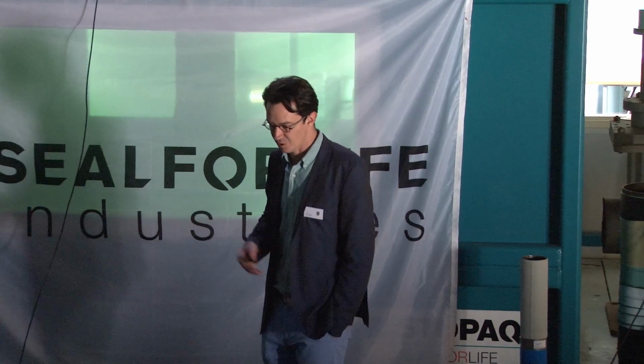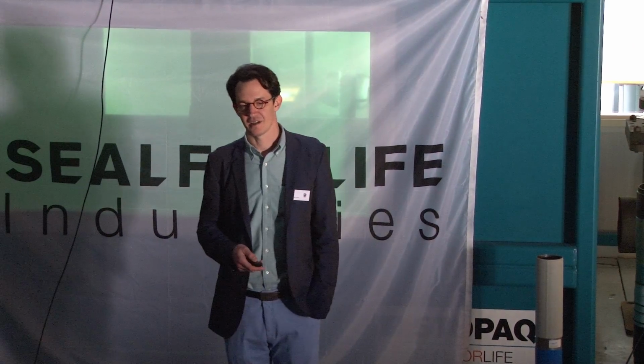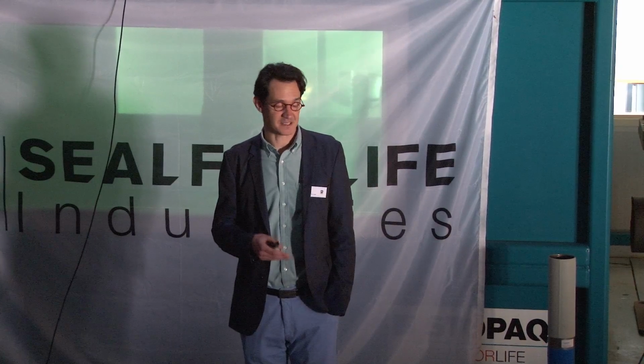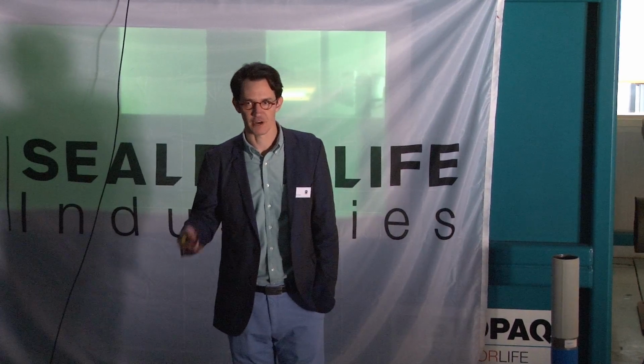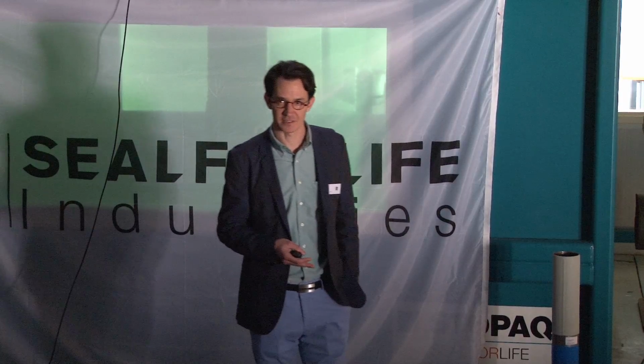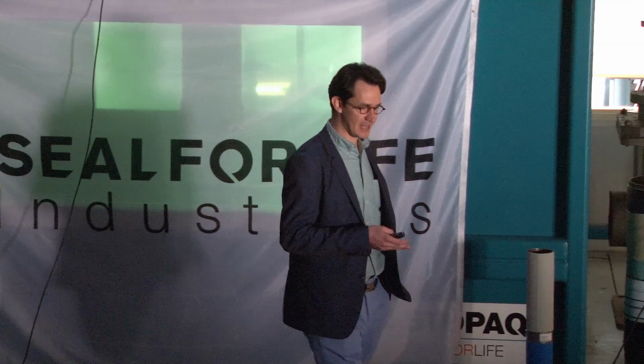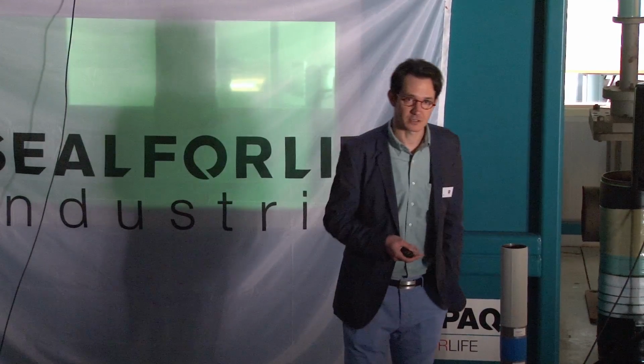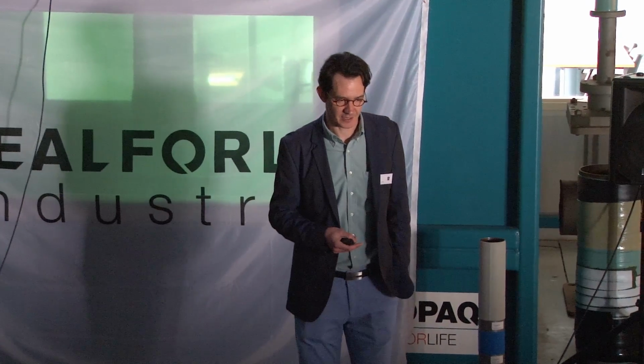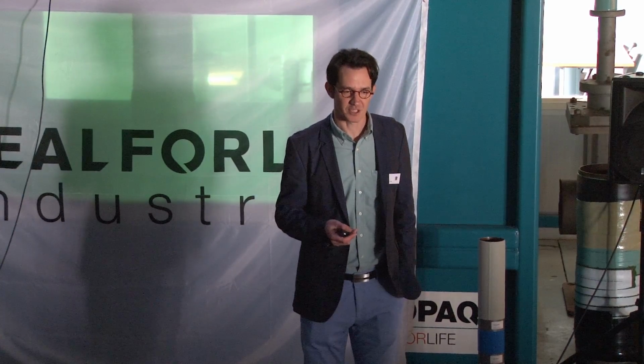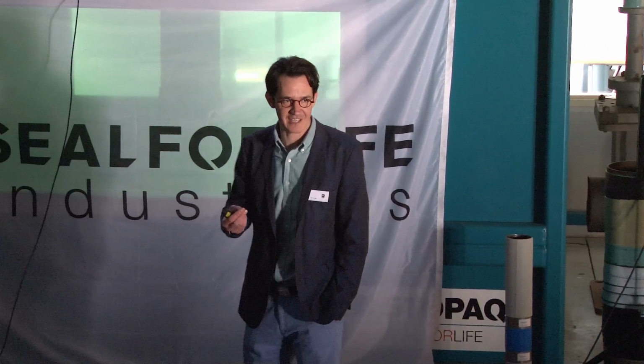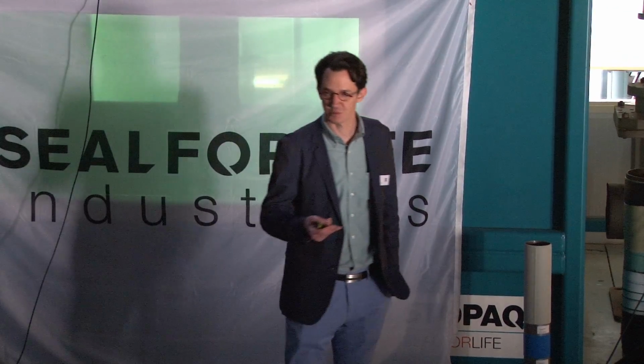Coatings, of course, protect pipelines and all kinds of steel structures against corrosion, and in the event that they age or crack, would they self-repair? Now, in the past, it's been worked on a lot, especially in the liquid coatings, where they would put these micro capsules filled with another coating inside, and if they do crack, the micro capsules will crack as well, self-heal, and you would still have protection.